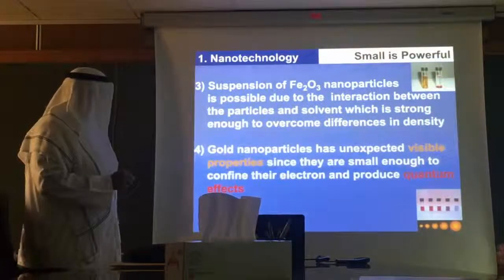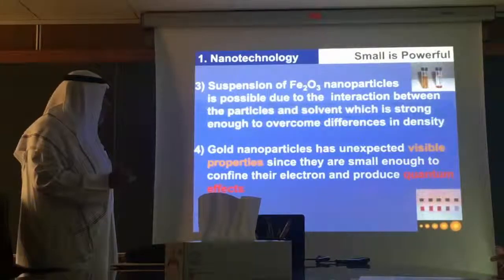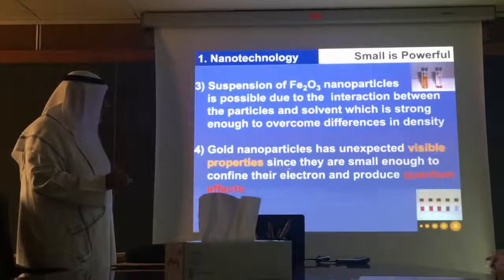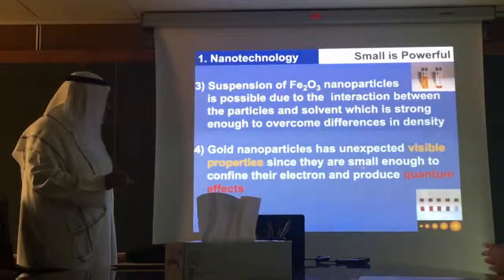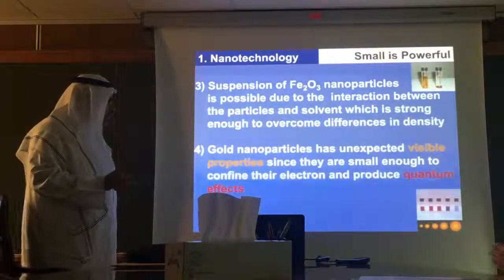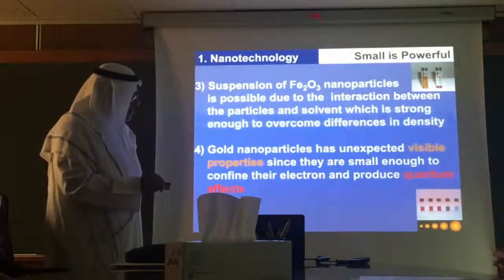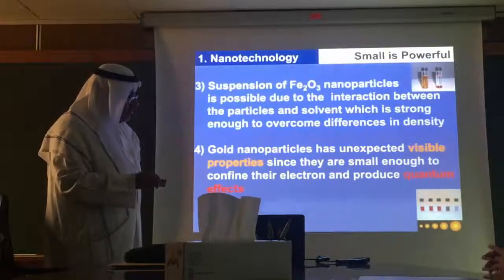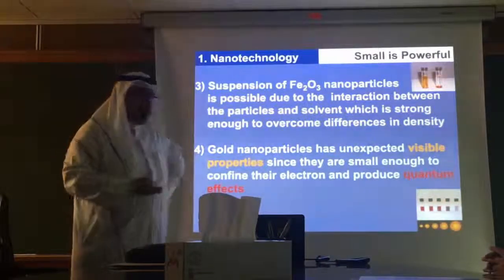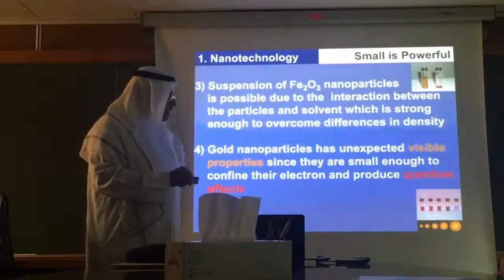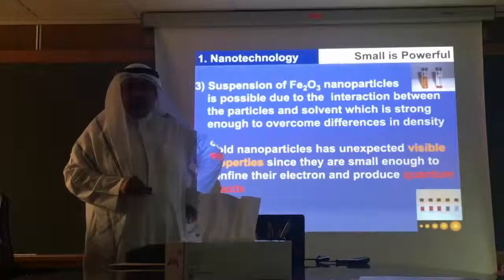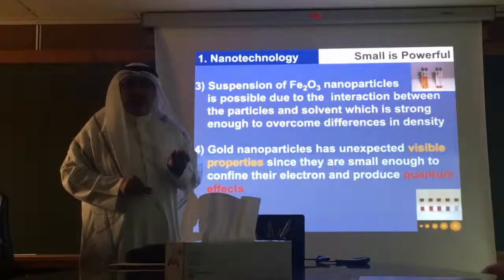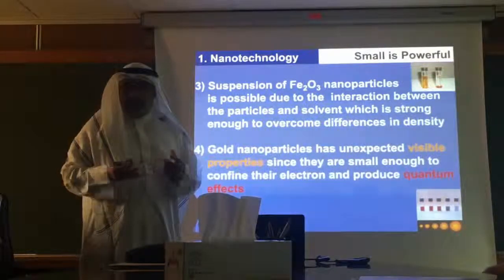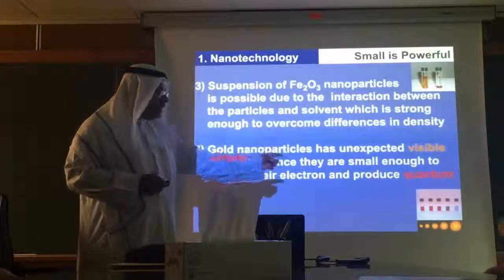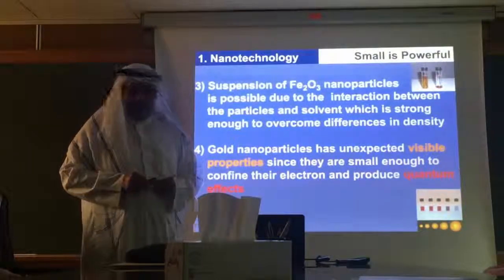Also, gold nanoparticles have unexpected visible properties, since they are small enough to confine their electrons, producing a quantum effect. This is also the quantum effect of gold nanoparticles. They are no longer yellowish, by the way. When you make gold small, you change its color. When you see it as a powder, you see it yellow because the particles are aggregated, actually. But when you suspend it in solution, you will see a different color.